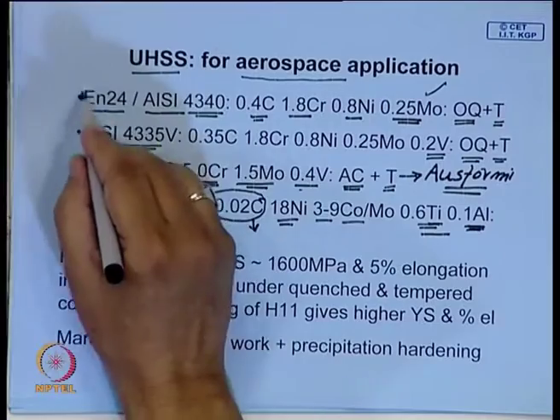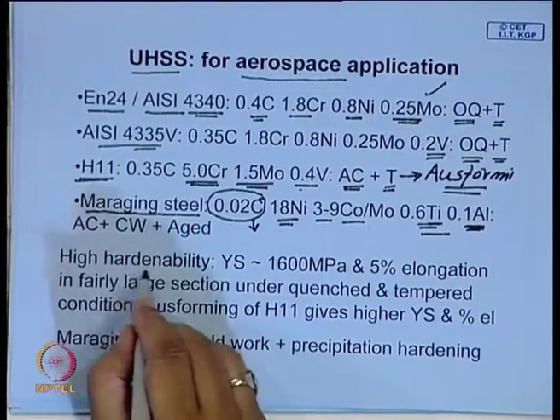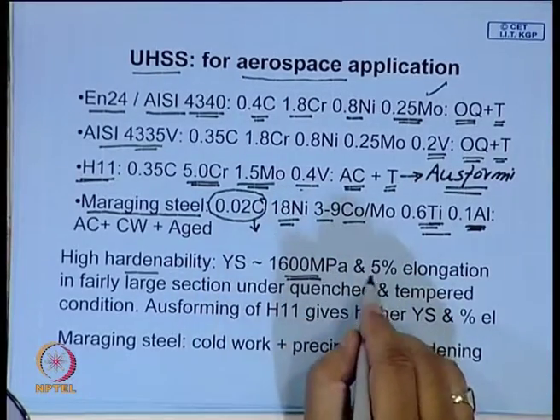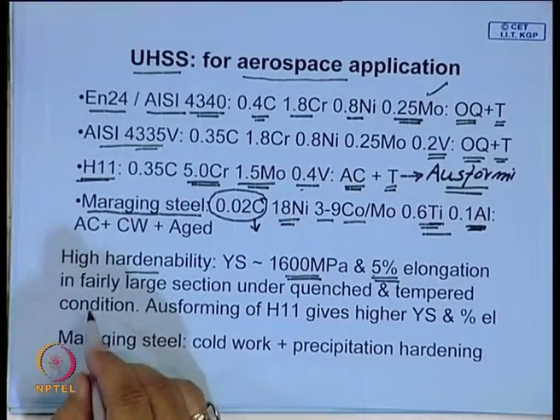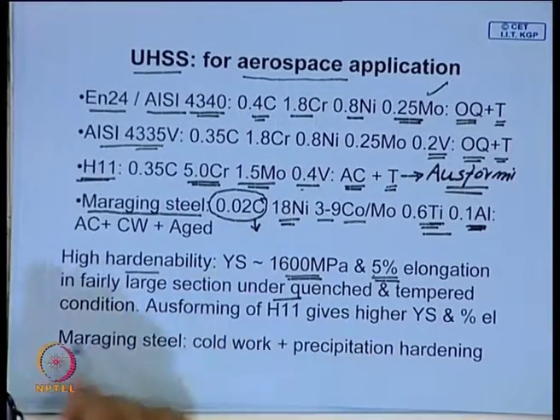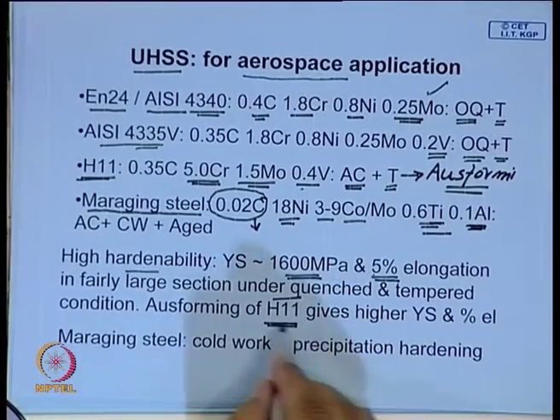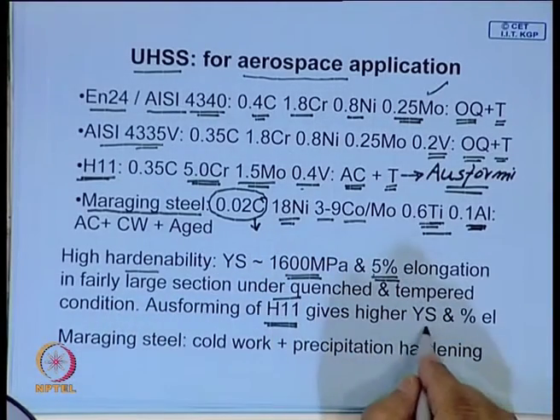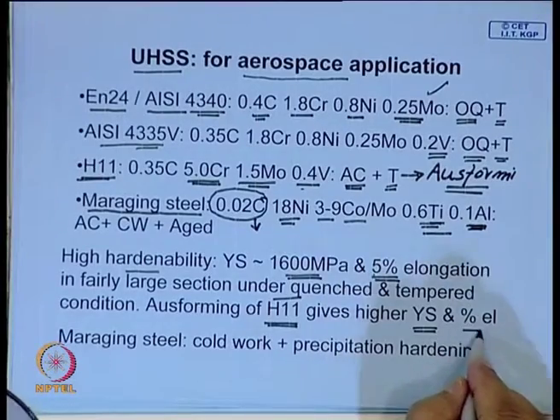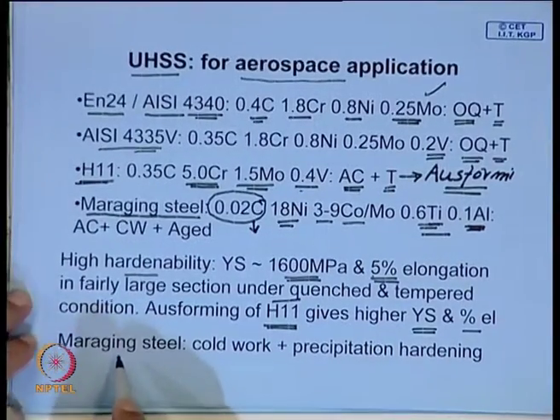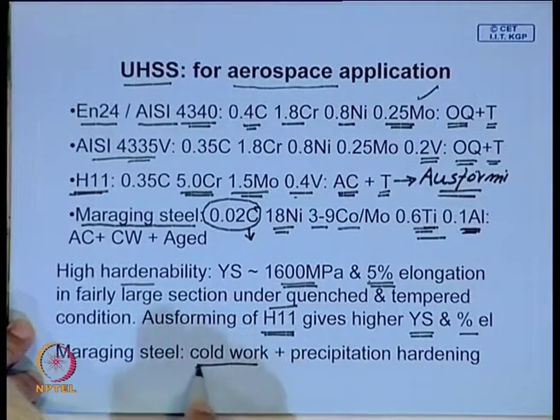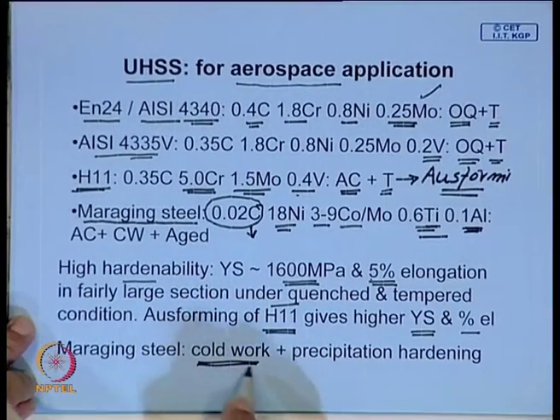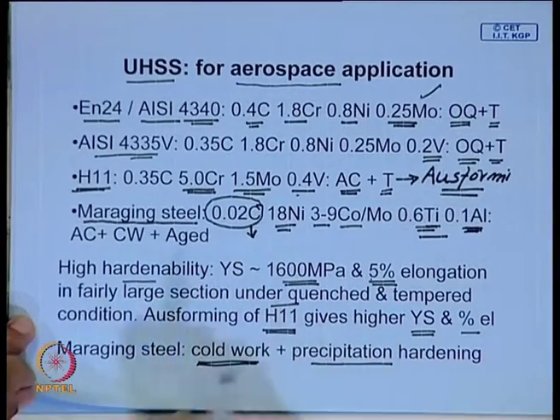Now, all of these steels, in this case of course, they have high alloy element. So, they have high hardenability and you can always get strength of the order of GPa, you have 5% elongation in fairly large sections. And as I mentioned here, this is amenable to ausforming and you can get even higher yield strength and ductility. Now, maraging steel, we mentioned that here martensite is soft, it can be cold worked and then it can be given precipitation hardening heat treatment.